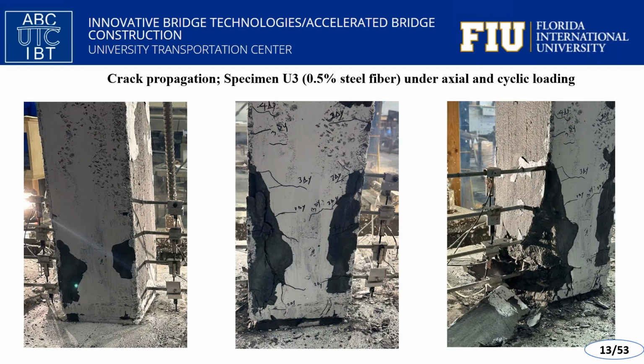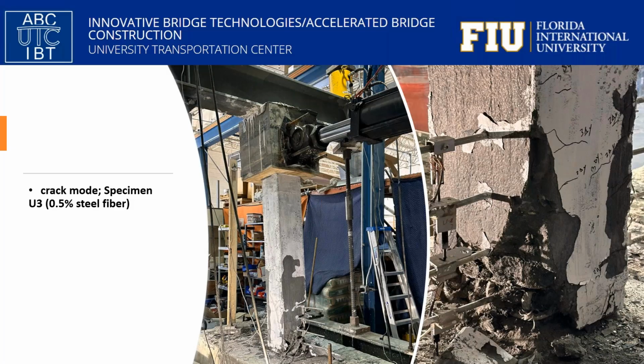Here you can see the crack propagation of the third specimen, which had 0.5% steel fiber. Horizontal and diagonal cracks were more prominent compared to the specimen with 2% steel fiber. Wider cracks and less effective control of crack propagation were observed. Spalling of concrete became evident, especially near the compressive zone. You can see the final deformed shape of the column at 7-inch lateral displacement, where localized crushing and widening of cracks occurred.